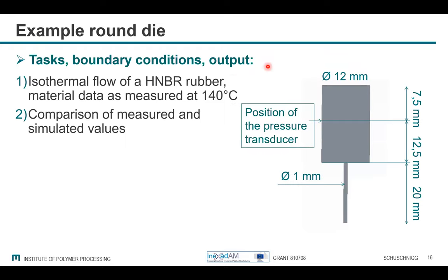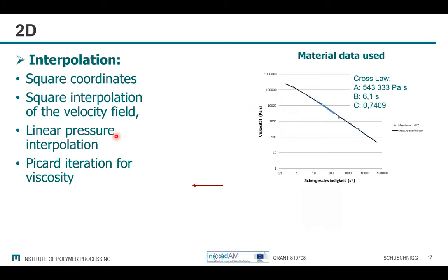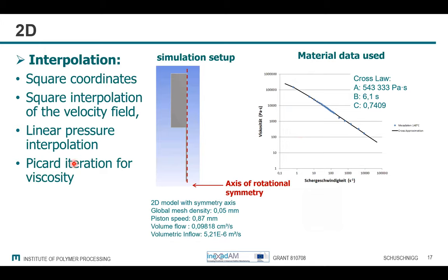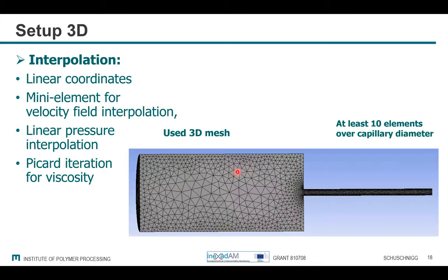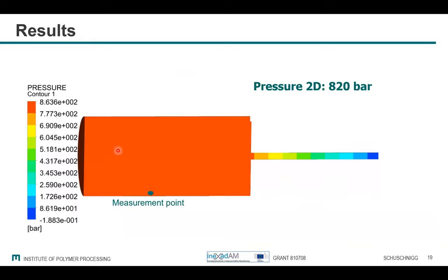Another example was the round die with different tasks and boundary conditions. And I want to compare the measured and the simulated results. I have a 2D simulation where I have an axis of rotational symmetry here, and I have the viscosity data, and I get out the results of it. Then I have a 3D setup. In this case, I also have to refine the mesh to a very small size because here most of it happens. And you can really see here in the cylinder, there's nearly no pressure loss. And most of the pressure loss starts in the round die.